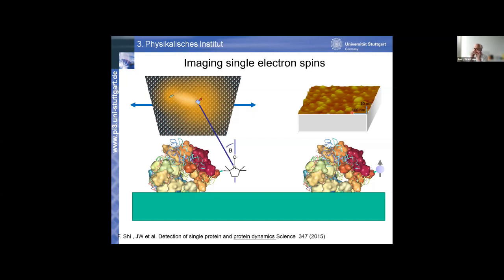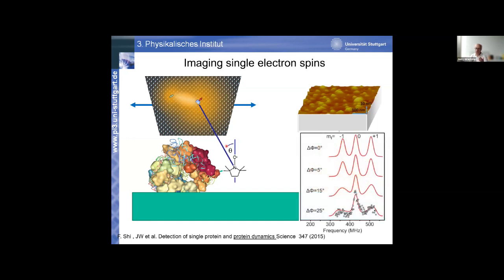I was already saying that these NV centers, and most defects in solids, are vector magnetometers, which means you can not only measure the strength of a magnetic field, but you can also measure its orientation. This comes from the fact that the electron spin is pinned by a crystal field, which is given by the structure of, in this case, the diamond. So you can, for example, measure this angle theta. That's what I'm showing you here. I'm not going into details because one would need to interpret these spectra in detail, but just to give you an idea of the principle of the technique.